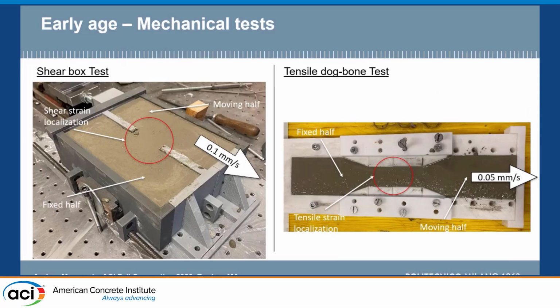It is based on shear box tests and tensile dog bone tests. Both tests work with one half of the sample that moves against the other. In particular, for the shear box test, this half slides against the fixed one, generating shear stresses in this cross section. Whereas for the tensile test, one half moves away from the other, generating tensile stresses on one of these cross sections with reduced area. The movement is generated by a motor that moves with constant velocity.